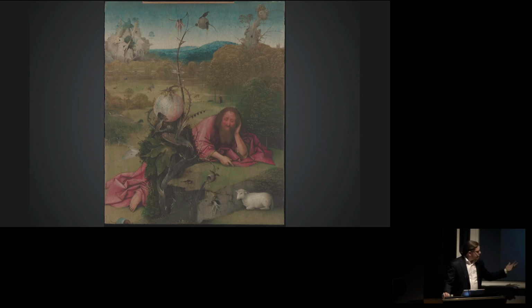So the next aspect of data fusion is that we don't just use a single kind of imaging. In this case, we've also used an infrared reflectography camera called an OSIRIS camera. This is operating at around 750 nanometers wavelength of light. And what this means is that the light scatters dramatically less, and therefore is able to move through this translucent binding medium, the oil, which is dried, probably linseed oil, to let us see what's behind it.